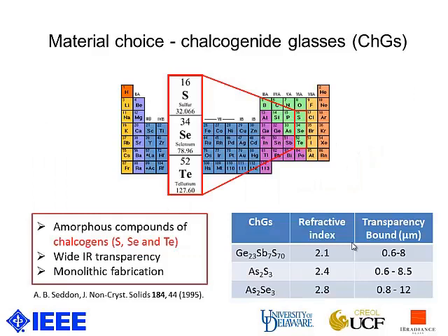For materials, we would like to choose chalcogenide glass. Chalcogenide glasses are amorphous compounds that contain chalcogens like sulfur, selenium, and tellurium. They have wider mid-infrared transparency, and also through tuning the composition of elements, the optical properties like the refractive index can be easily adjusted. Another benefit is that chalcogenide glasses are amorphous, so they can be monolithically fabricated on different kinds of substrates.